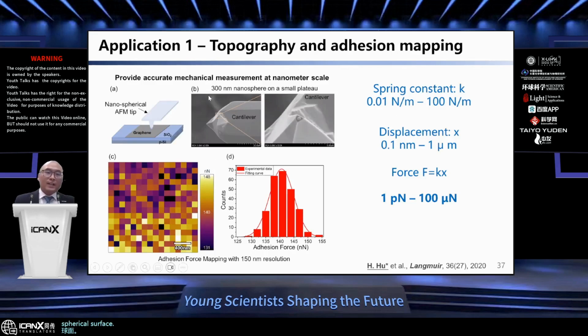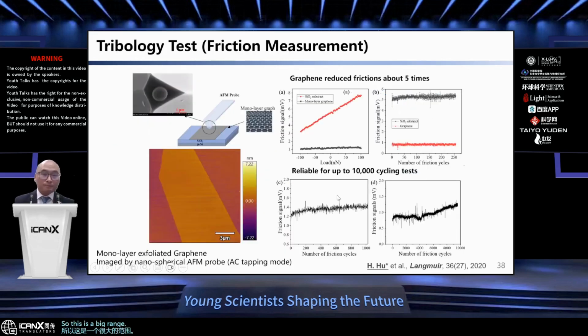With this, we can take advantage of the small size. We can provide 150 nanometer spatial resolution, in this case, for adhesion force mapping between two surfaces. If we do a quick calculation, we can design the spring constant of the micro cantilever from 0.01 Newton per meter to 100 Newton per meter. If we can detect the displacement in the vertical axis from 0.1 nanometer to 1 micron, we can achieve a force range from 1 piconewton to about 100 micronewton. This is a big range for measurement.